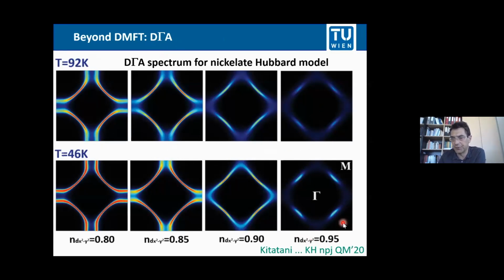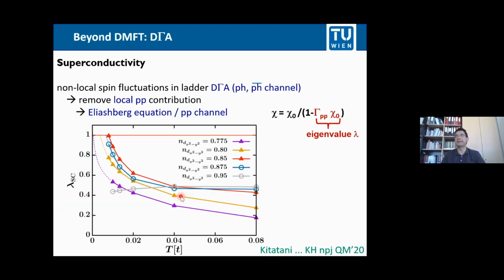And here you see a pseudo gap. So the undoped compound has a pseudo gap, and the doping for the superconducting regime is about here, where you don't have a pseudo gap on your Fermi surface. We can then also calculate the superconducting critical temperature.